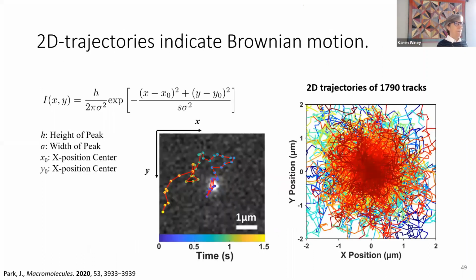So from the two-dimensional trajectories, this is nearly 2,000 tracks, all starting arbitrarily at 0, 0. You can see these are random. There's no bias here. They're not drifting. So this is a good data set. And this is how we identify the center of the peak, the center of the intensity.